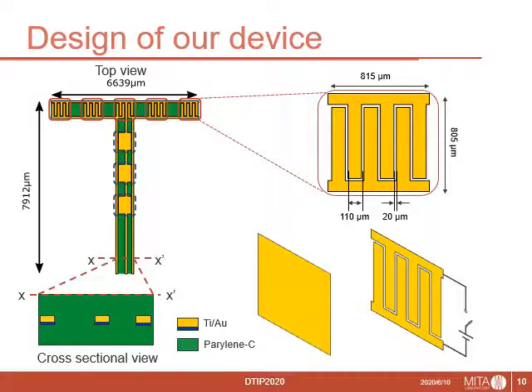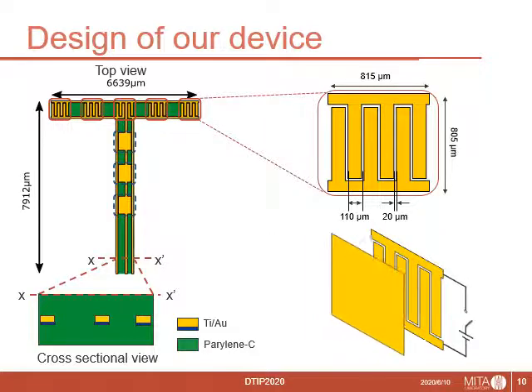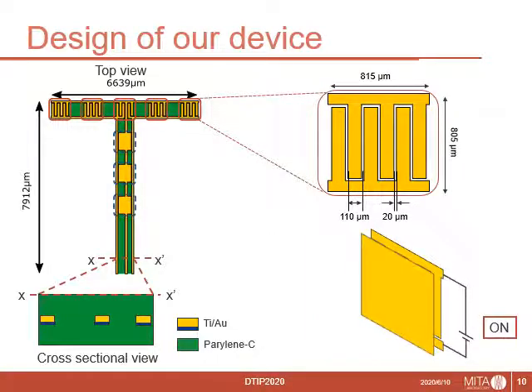This is the design of our proposed device. It has a T-shape, and its electrodes are sandwiched by flexible Parylene-C films. There are 5 actuators on the horizontal bar and 3 conductive areas on the vertical bar. The lower end of the vertical bar is connected to a driving circuit. The actuator is interdigitated electrodes. Its dimension is 815 micrometers by 805 micrometers. When the actuator faces a conductive surface, a voltage supply generates adhesive force.